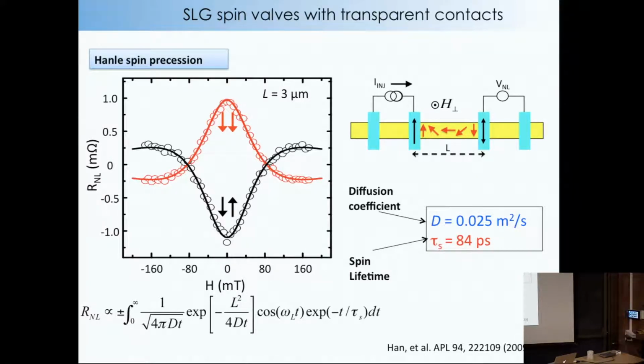And what you can do, so the way that you deal with this theoretically, and this is not the most fancy way, there's more fancy ways, but the idea is you have a term that comes from the electron diffusion, so D is the diffusion constant. You have a term which is from the Larmor precession, the precession of those electrons. And then you have a term from the decay, the depolarization, the relaxation of the spins. And you put all that together because it's a steady state, and you can get these curves.